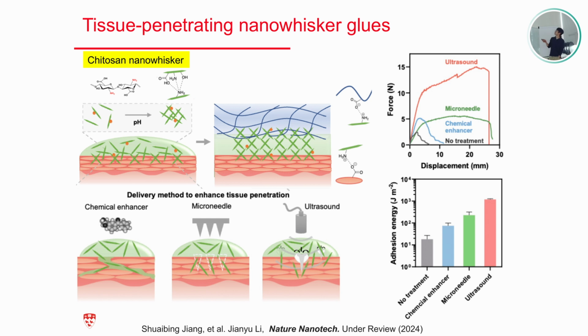So that is the result. We combine our delivery approach and this kind of nanowhiskers particle, and we can achieve a very high adhesion energy between the hydrogel and also the skin tissue. Like in this case, among the three testing methods, they're all effective, but again, the ultrasound stands out in terms of the overall adhesion energy performance.